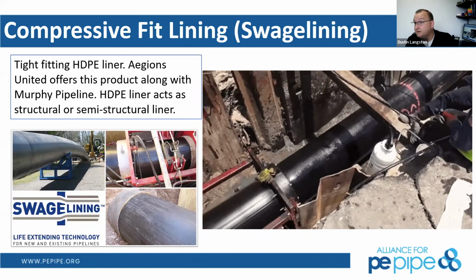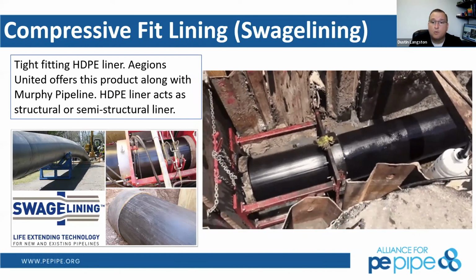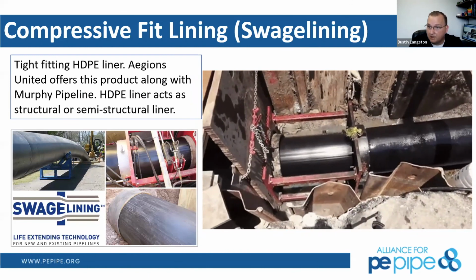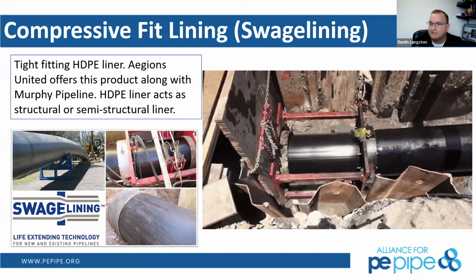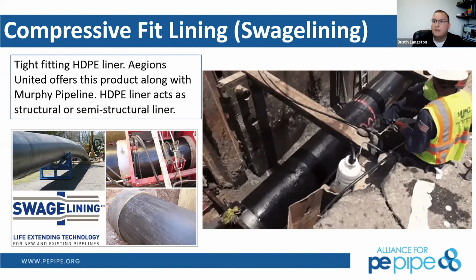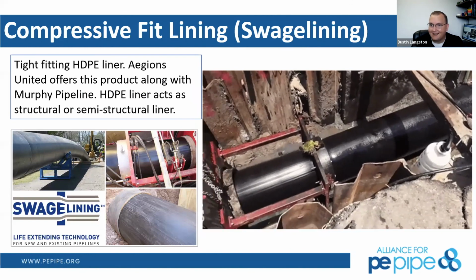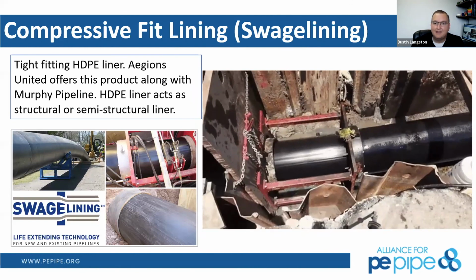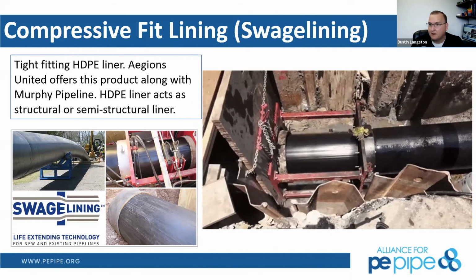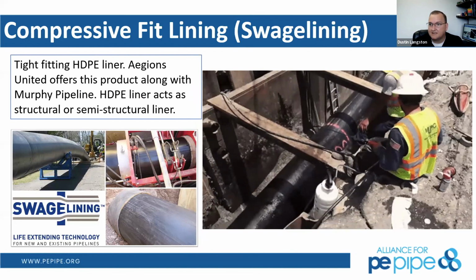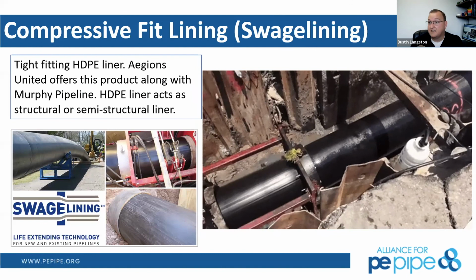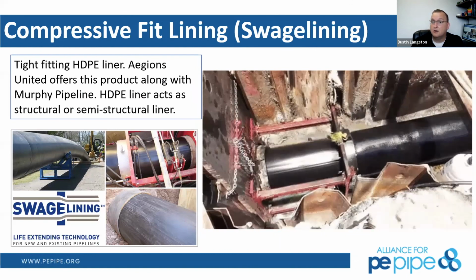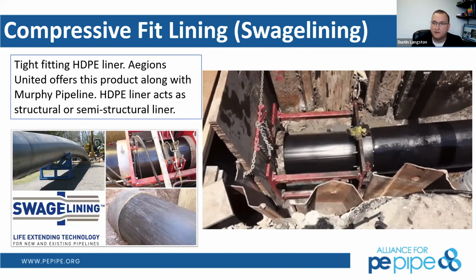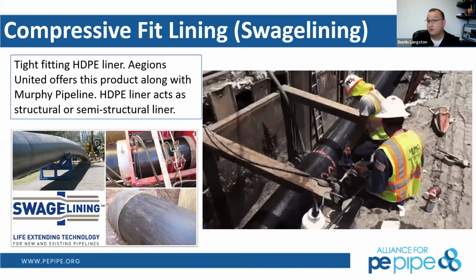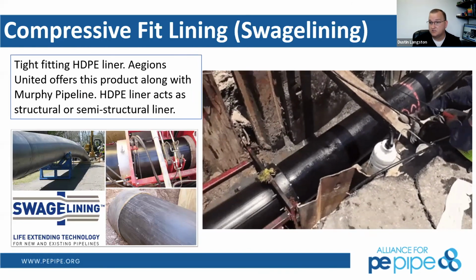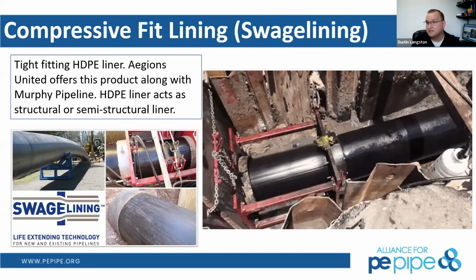Here's the compressive fit, what we call swage lining, where we're going to take a slip line, but we want to maximize the inside diameter of that slip line. It's easy to pull in a smaller slip line and grab the annular space. In this case, we don't want to do that. We want every millimeter of that inside diameter for flow. And so we're going to take a pipe size of polyethylene that's larger than the inside diameter of the host pipe. We're going to take it through either a set of box rollers or a swaging tool, which is just a die. That's what you see here.